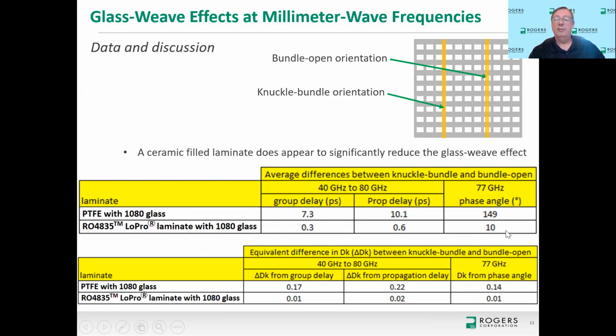And here you can see the phase angles even better than our previous study with the spread weave. This is an open weave glass, obviously, and unbalanced, the 1080 glass. And we have very little glass weave effect in this case at 77 gigahertz, so only 10 degrees difference in phase angle. Again, the table of information below is the same format as shown a couple of slides back, where this is really just the extracted dielectric constant differences based on the data on the top table of information.